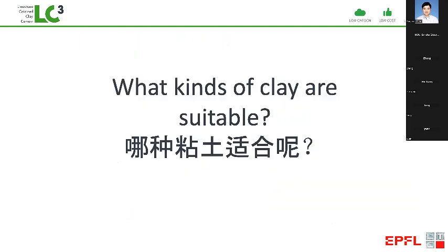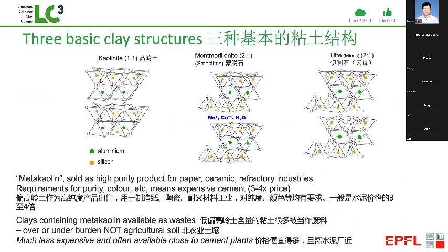Now, the first question is to look at what kind of clays are suitable. We need to have a certain amount of this mineral kaolin. So this kaolin type clay is what's called a 1-to-1 clay, which means it has one layer of silicates and one layer of aluminates. And when it's calcined, that's to say heated to 800 degrees, this structure becomes disrupted and both the silica and alumina are available to react.